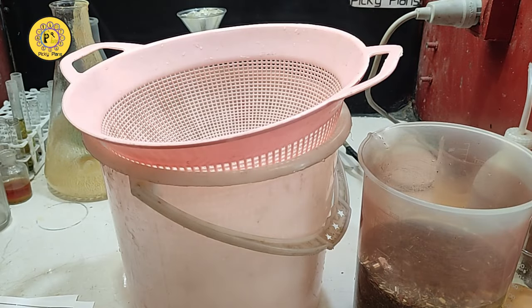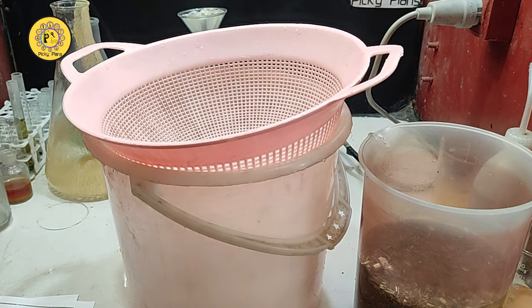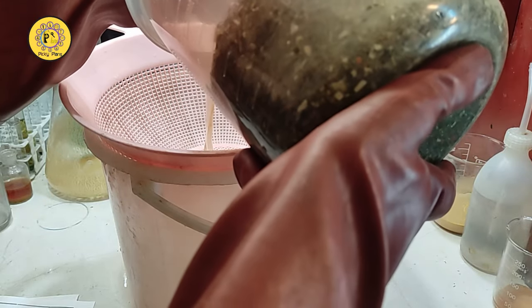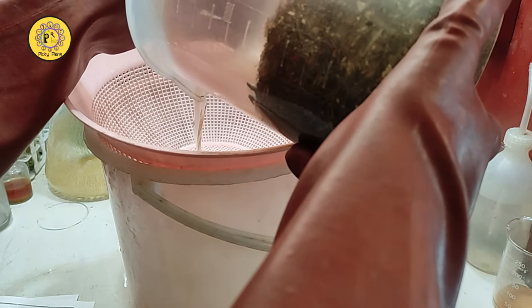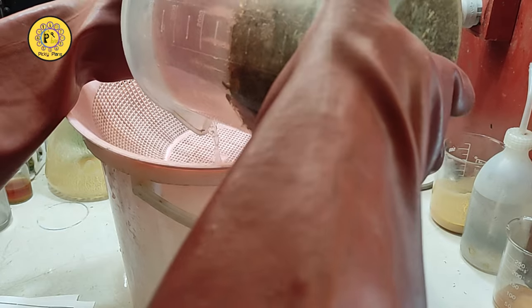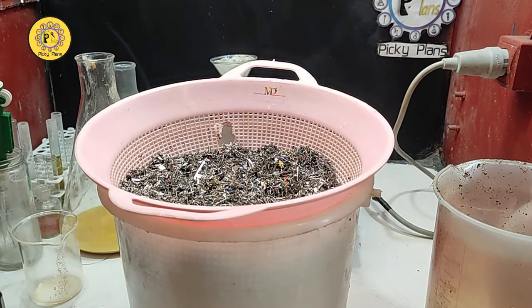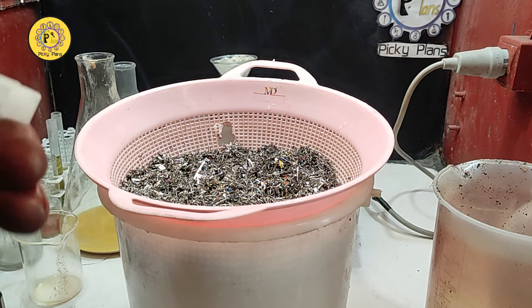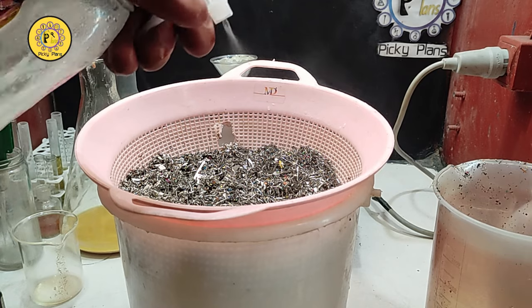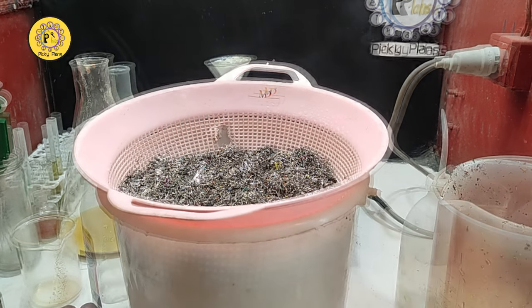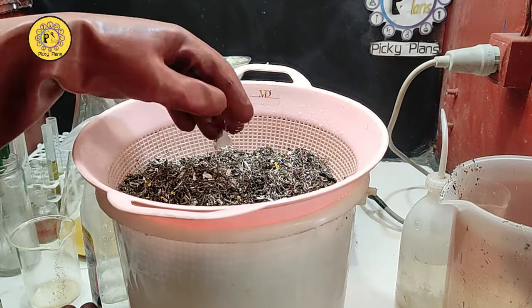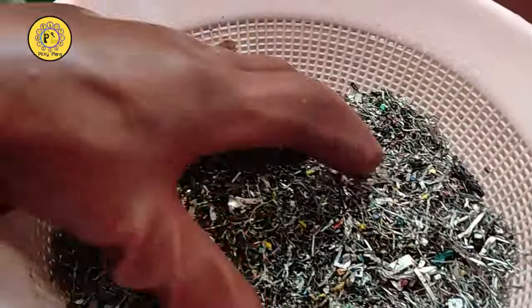For such low grade pins, you really don't want to leave your pins inside this solution for a long time. This solution has an inhibitor for copper, but it will prevent copper dissolution only up to a certain point. After that, copper starts getting dissolved in the solution. So it is not recommended to leave this on the low grade pins for more than 5 minutes. And now let's check the pins out to see how they have been stripped.